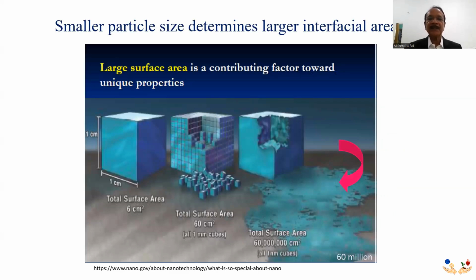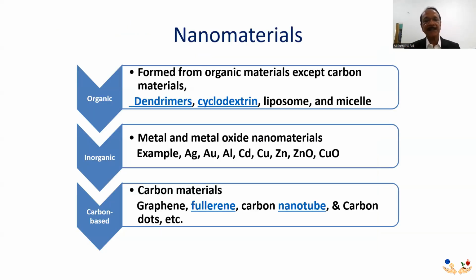The smaller particles have a larger surface area. For example, if you take 1 centimeter by 1 centimeter, the surface area is only 6 square centimeters. Whereas if we take 1 millimeter by 1 millimeter, it becomes 60 square centimeters. In the case of 1 nanometer, this will form an area of 60 million square nanometers, such a huge area. And this area is responsible for a broad activity. And that is why I say that nanoparticles are very, very active.